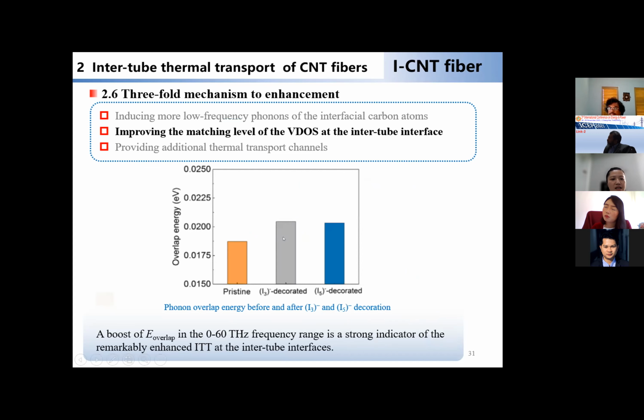The second mechanism is improving the matching level of VDOS at the intertube interface. We can check it by phonon overlap energy that represents the matching level. We can see a boost in the 0 to 60 THz frequency range, a strong indicator of the remarkably enhanced heat transfer at the intertube interface.